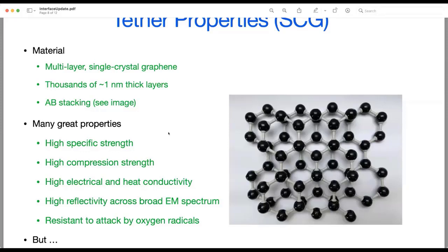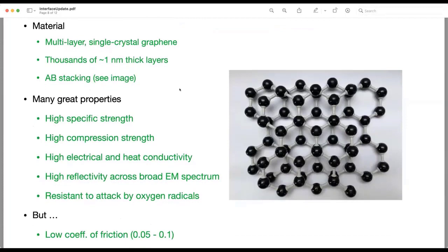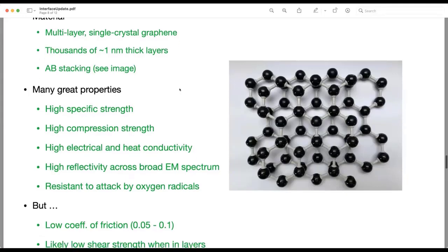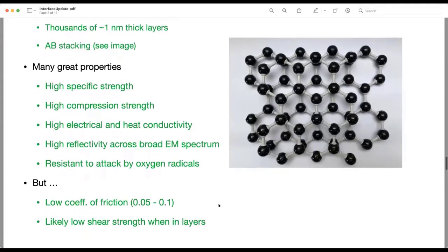So we know that single crystal graphene has a lot of great properties. It's a high specific strength, high compression strength, great electrical and heat conductivity, high optical reflectivity, and in fact, it goes all the way across the electromagnetic spectrum. It seems to be resistant to attack by oxygen radicals, so it's good in the atmosphere. However, it looks like it has a low coefficient of friction, so between maybe 0.05 and 0.1. And you recall I said that we need 0.1 or greater.